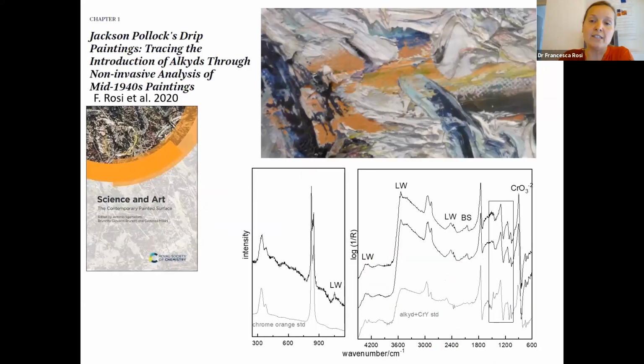In particular, we detected the presence, with the chrome orange, of an alkyd medium in the painting Ice in the Heat. According also to historical records, the winter between 46 and 47 is a sort of turning point for Pollock's style. He started experimenting, and this non-invasive data confirmed that he started experimenting with alkyd medium before 47 with these two paintings. But then he realized that with the discovery of this medium, he had the opportunity for expressing mainly his action painting, his action art, through the dripping, and so after 47 there is the permanent appearance of the alkyd media in his painting.